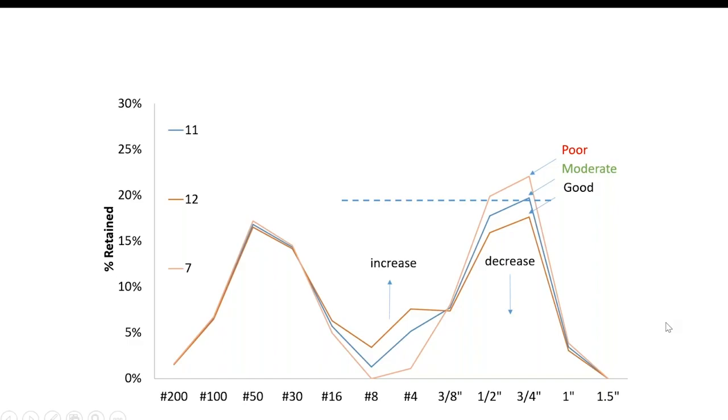And we've done a little bit of work. And Gary, what we're finding so far is that as long as you're within the tolerance using smaller stone, there's no difference in performance. There's no difference in paste needed, no difference in workability, and no difference in shrinkage. I can try to explain why I think that's happening if you want. But what we're saying is that this larger stone is an option. Why I think it's an option is that if you noticed here, there were two options, this going down and this going up. Another option would be for this to go down and something larger to go up. Does that make sense, Gary? You follow me? Yes. Okay.